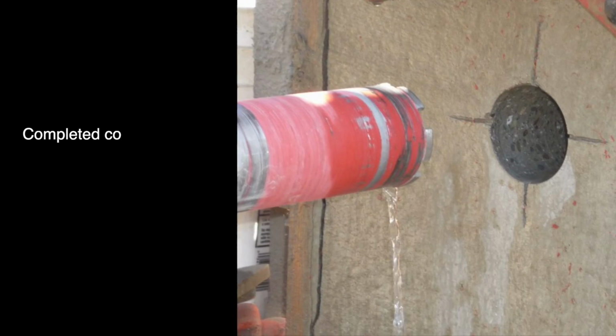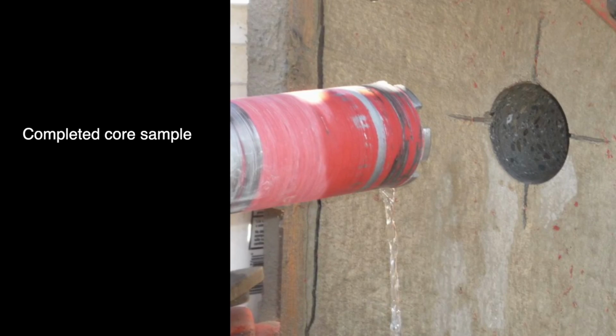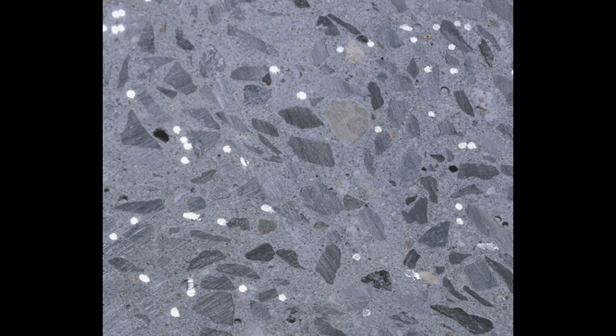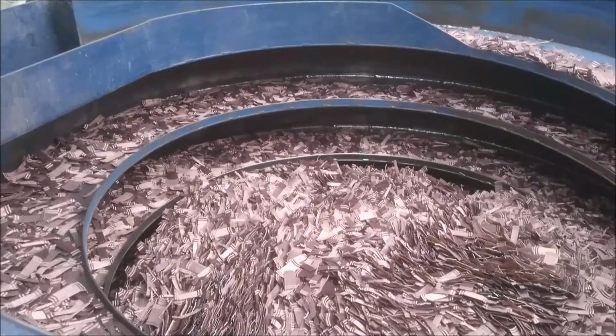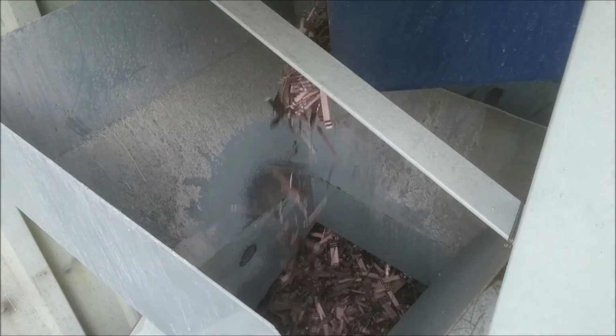It's redistributing loads. If you want to test steel fibers concrete, you can do it also by taking cores, crushing them, testing the strength of the concrete, and also then taking the fibers out of that core, so that you can count the number of fibers and determine the amount of fibers in this given place. Because you know that with this quality of concrete and this number of this fiber type, you should get the strength that you need. One of the problems is that if you take a core, you have a small volume, and one fiber more or less can change quite a lot the dosage that you calculate.